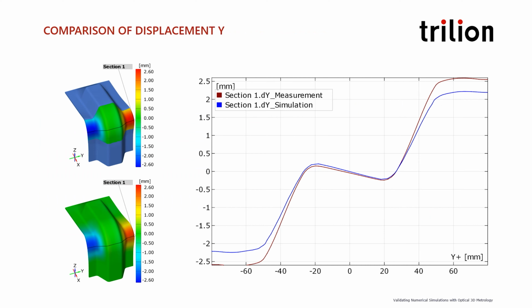After the ARAMIS test, a comparison is made between the simulation and the reality. ARAMIS data on the top, simulation on the bottom. A section line is constructed and the displacement across the profile in the y direction is plotted in the diagram. Notice the disparity between the simulation and ARAMIS at the outer edges, nearly 0.5 millimeter. It's quite large.